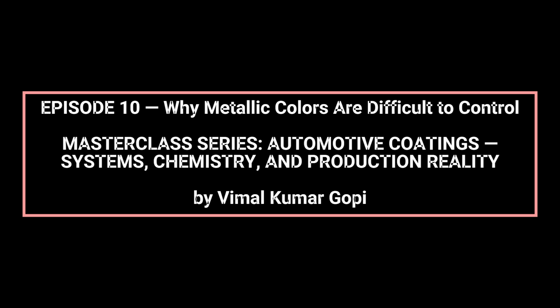At the formulation level, solvent balance is the primary driver of metallic stability. Fast evaporating solvents increase early viscosity and restrict flake movement, often leading to poor flop, dull appearance, or mottling. Excessively slow solvent systems extend film openness, allowing flakes to reorient too long, increasing the risk of flooding, striping, and cloudiness. Achieving the correct evaporation profile requires precise tuning across multiple solvent fractions.